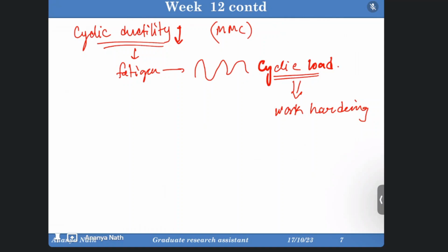Where the stress is low means it's the high cycle fatigue test, where the applied load is low. But in case of strain control, where the strain is less, strain is less means we are going for higher stress for very low time. We are not letting the matrix elongate at that particular time. So it will just fail after a few cycles as the load is so high. So that is strain control.